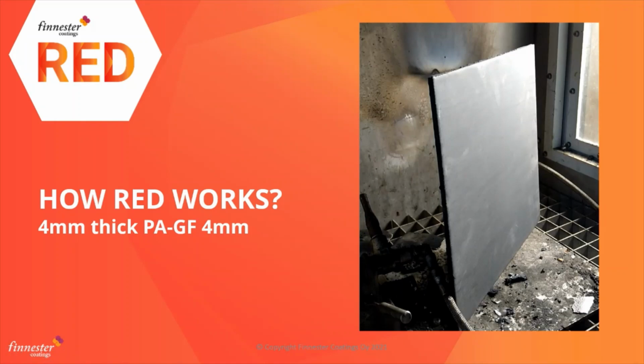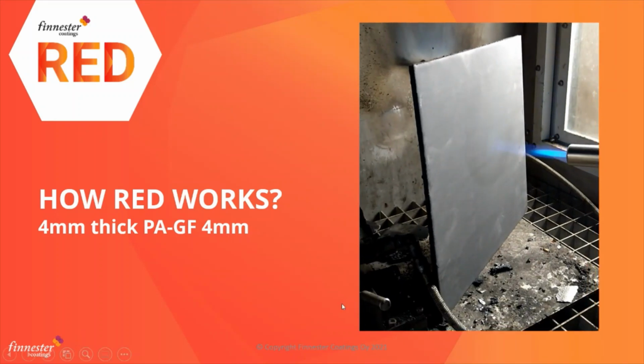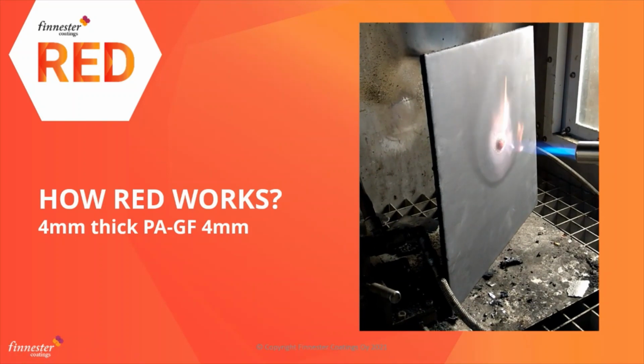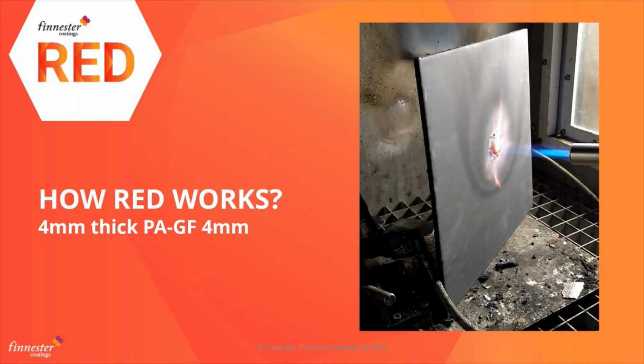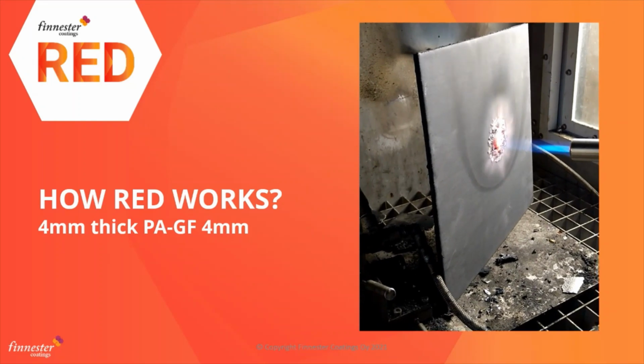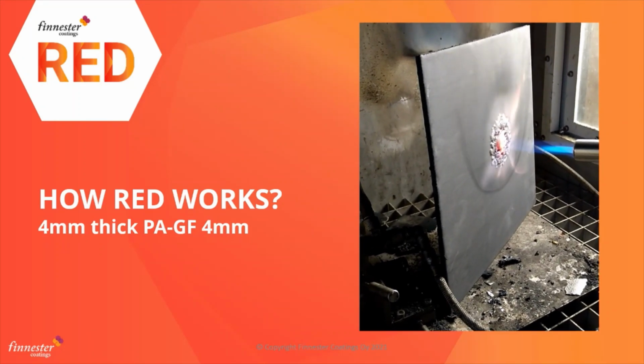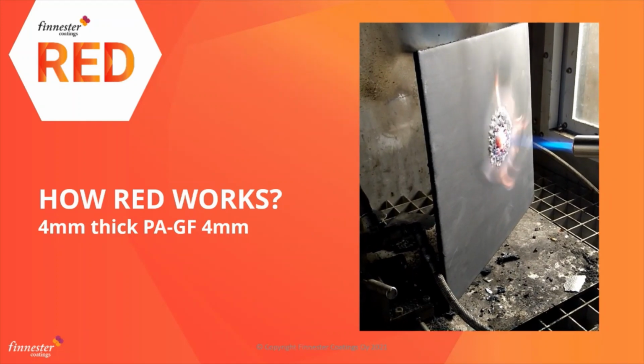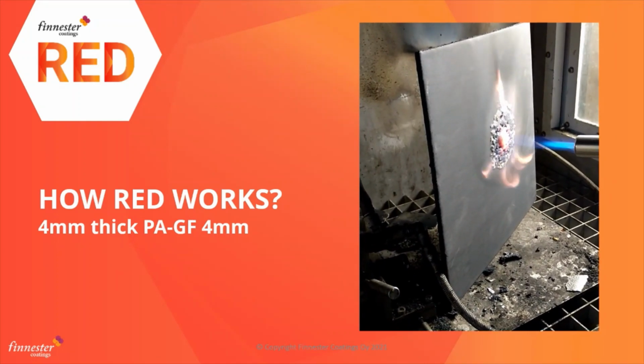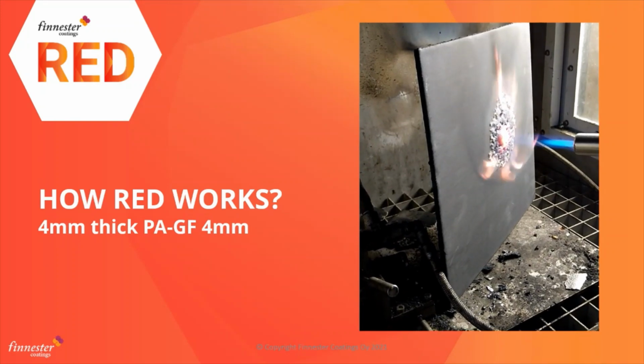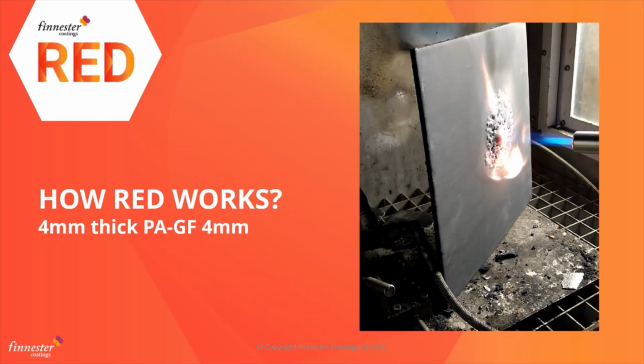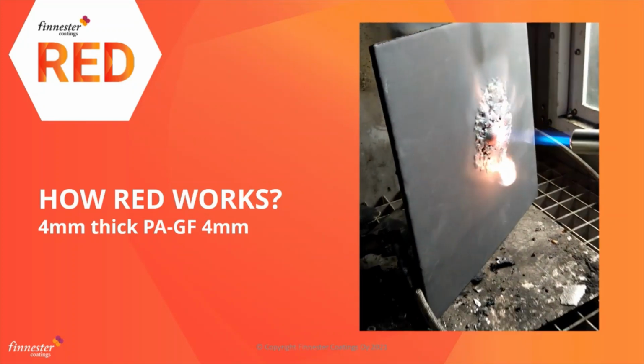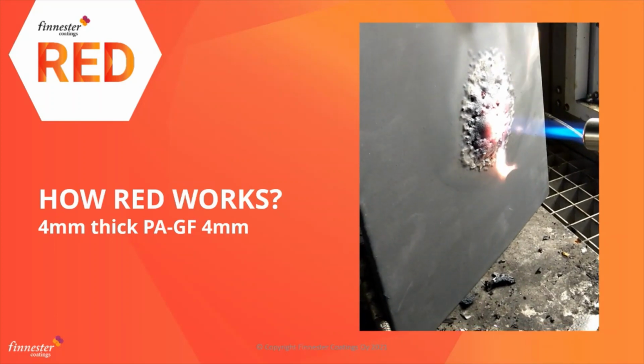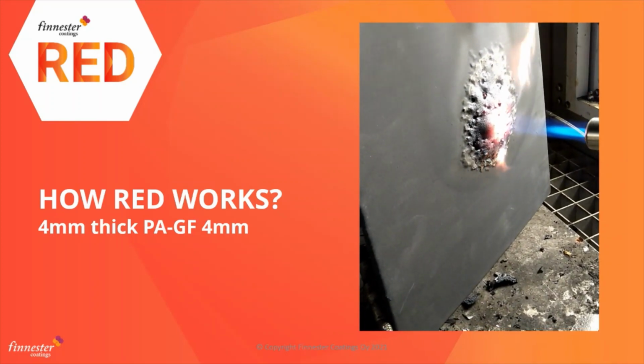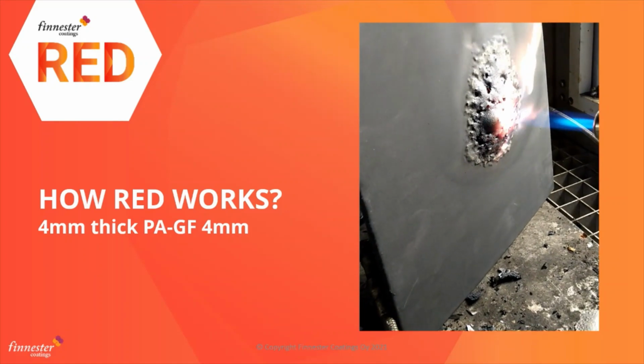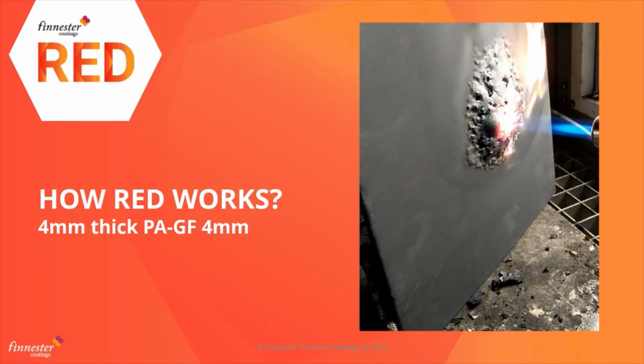So red, in this case, is a two-layer coating. Underneath is the intumescent coating, and on top you have a ceramification coating. When the heat is introduced to the surface, it will start to burn, and that's fine. The organics are going to burn away, but at the same time, the heat will transfer to the underlying coating, and that starts to expand. So we have a double reaction. The top layer will turn to ceramic material, and the underlying primer coating will start to expand. This starts at 270 degrees, and it can continue up to 1100 degrees. And in this video, I hope you can see the video.